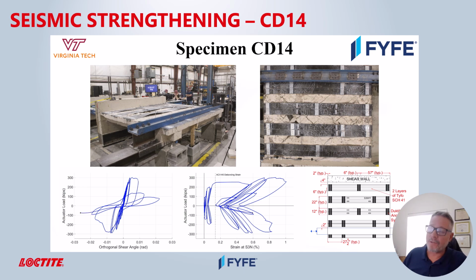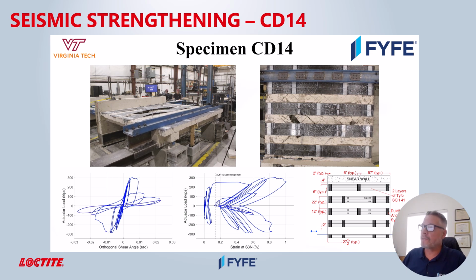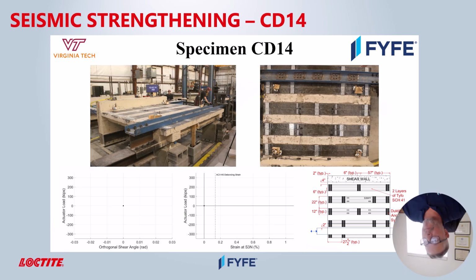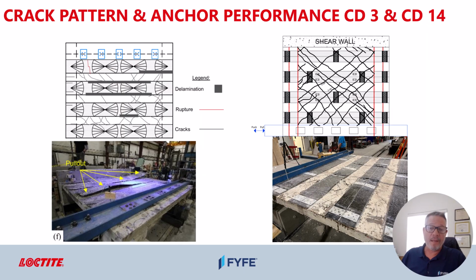You can see the strains are well above 0.8%. So in this specimen, we've got well beyond, in fact double, the strains that were recorded using the FRP anchors. We're able to achieve this using these ductile FRP anchor plates. Extremely improved performance and better failure mode.